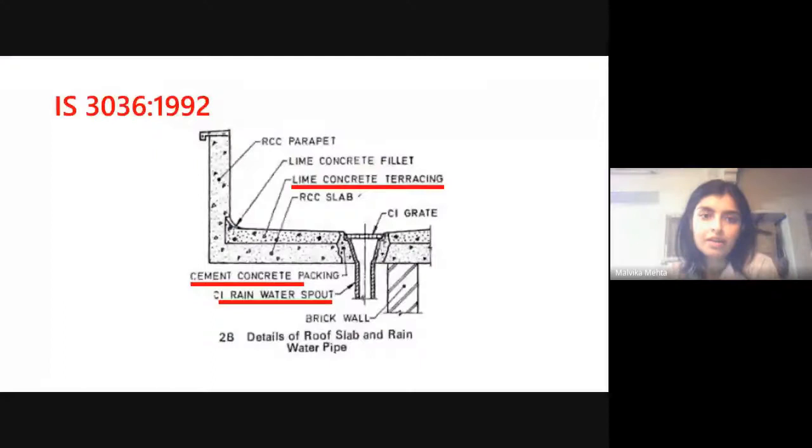Right, so I was just sharing that there were details like this, which were the go-to details in the 90s and the 80s. And of course, details like this today we understand very easily are designed to fail, where cement concrete is being used to pack and grout rainwater drains in a lime concrete terracing. So these were the transition period details as the construction moved from lime to cement, and these kinds of composite details were created, which at the time probably seemed fine, but now we realize such a detail would fail even with the best quality lime